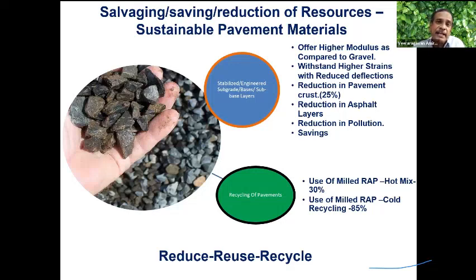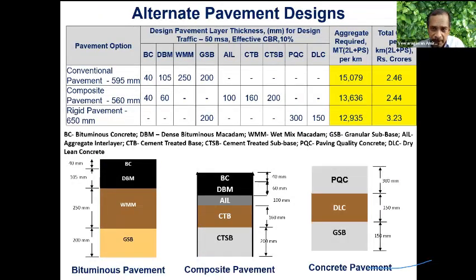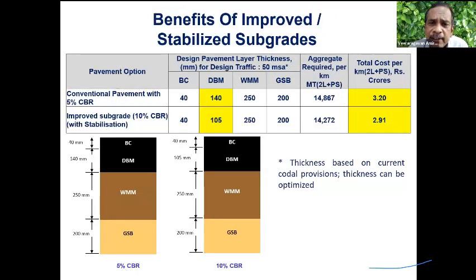But again, civil engineer has got a different role on characterizing the material. Even simple example, if I have a pavement which requires nearly 595 millimeter thickness for a subgrade of 10% CBR with 50 million standard axles, it will require 15,000 metric ton per kilometer for a 2-lane highway with a paved shoulder, 15,000 metric tons. On the other hand, if I have a rigid pavement, I require only 12,935 metric tons. I can reduce the aggregate consumption. If I can, simple, I don't do anything more. I don't bring in a new material in the upper layers. I am only stabilizing subgrade.